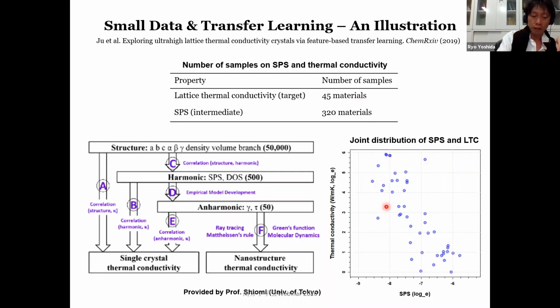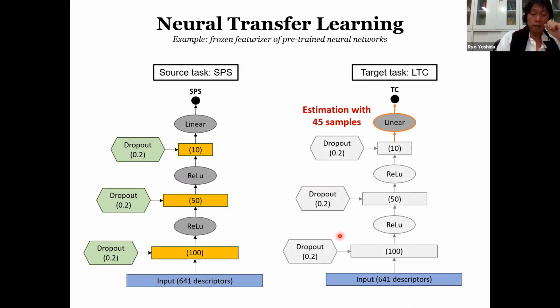As shown in this figure, these two properties exhibit a weak correlation. The SPS and thermal conductivity are shown on the horizontal and vertical axes. A very weak negative correlation is present. To overcome the hurdle of the limited amount of data, we applied the commonly used transfer learning with a neural network. Using the 320 data on the SPS, we trained a 3-layered, fully connected neural network, which is transferred to the target task of predicting thermal conductivity.